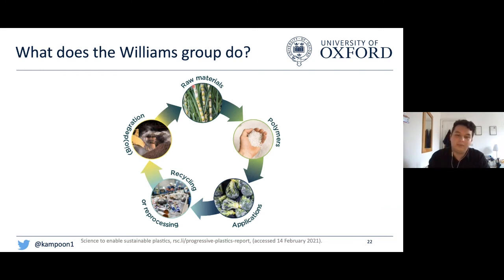So, going back to the Holy Grail I showed earlier, this material is a fantastic example because it's made from materials coming from castor beans, which are renewable as a plant, and carbon dioxide, which is a waste material. We can make an interesting tri-block copolymer with those, and we can take that polymer and tune its applications by changing the weight percent of CO2 in there.